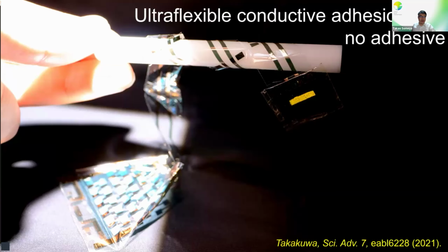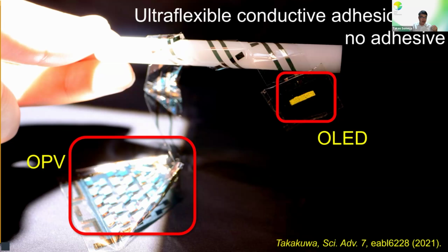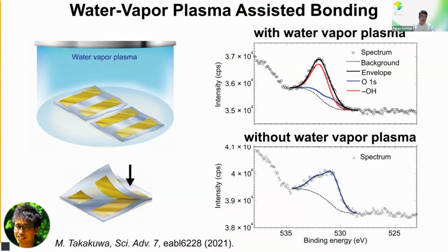And then I want to tell you the recent progress of system level integration utilizing the OLED, OPV, and also organic photodetectors. So even though individual devices could be manufactured on ultra-thin film, when laminated together the total thickness may increase, but the thickness is usually dominated by the thickness of glue or double-sided scotch tape. To maintain the total thickness to be super thin, ideally we want to laminate the individual films without using any glue. To achieve our goal, here is a new technique. That is water vapor plasma assisted bonding.